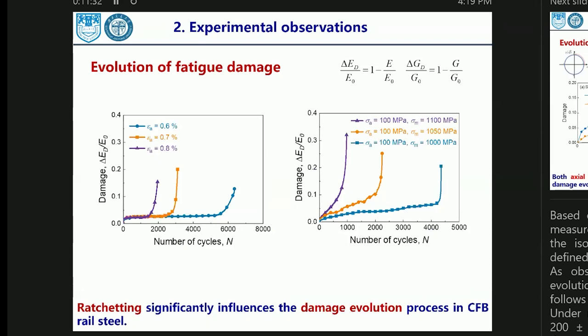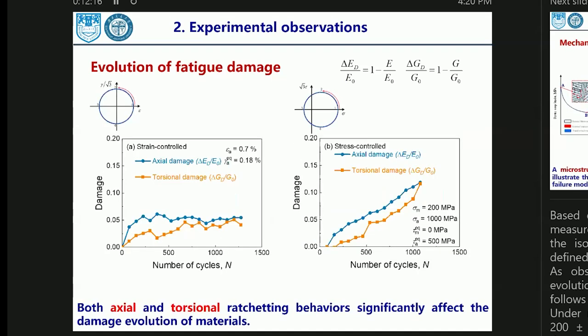Besides, we use the traditional way to evaluate the fatigue damage. We define the damage variable of the elastic modulus reduction, and also the shear modulus in another direction. We find that under the strain controlled mode and under the stress controlled mode, they still exhibit different trends. And with the existence of the ratcheting strain, the damage increases linearly with increasing cycle number. Also under the multi-axial loading path, we still find differences between the strain controlled and the stress controlled: they have different trends, and both the axial damage and the torsional damage have similar differences.